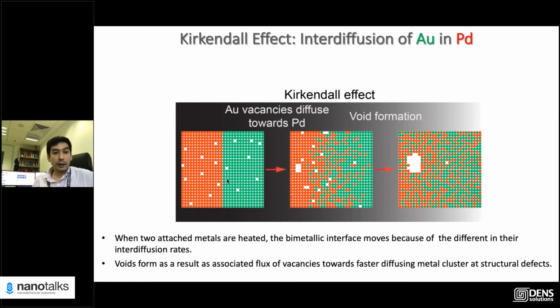And once you start heating them up, the interface between these two attached metals is going to start moving, right? This is because of the difference in their interdiffusion rates. One metal species diffuses faster inside another metal species, and as a consequence, you start forming voids. And why do voids form?